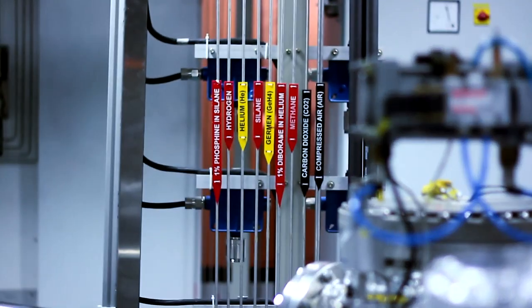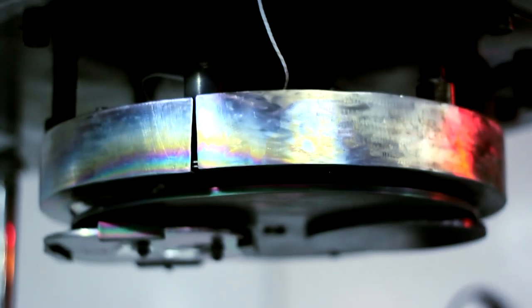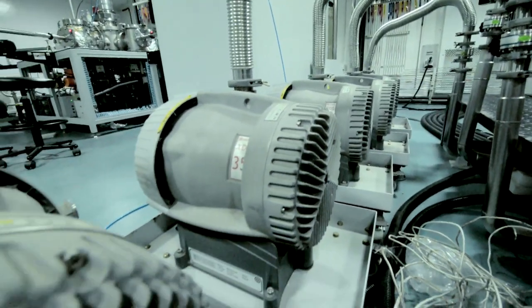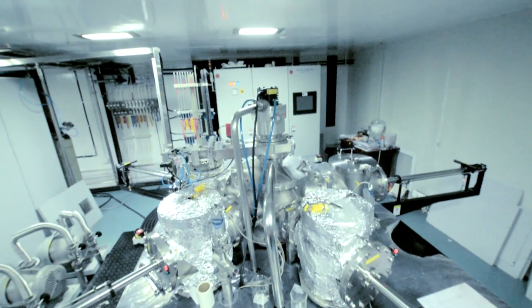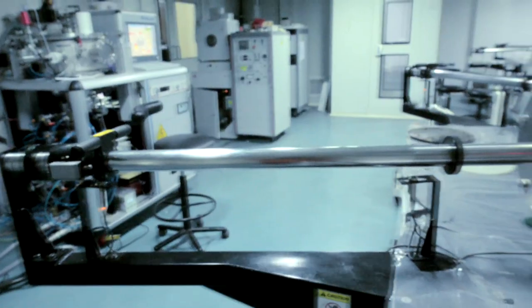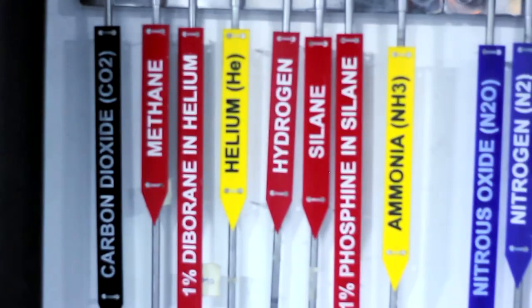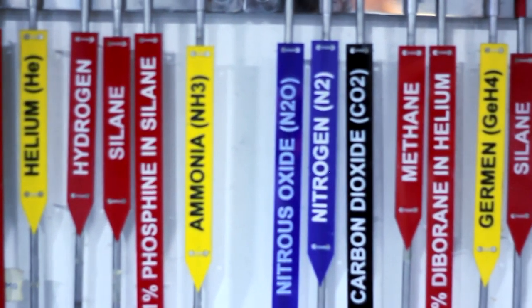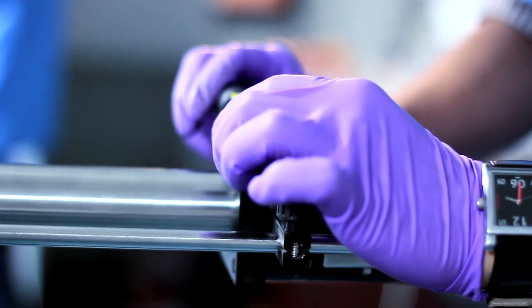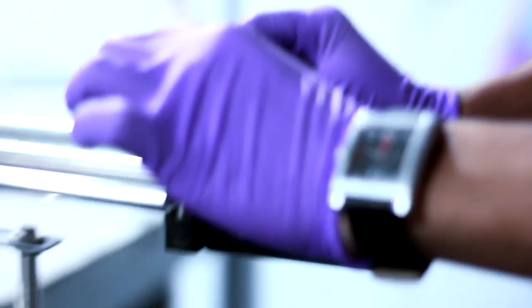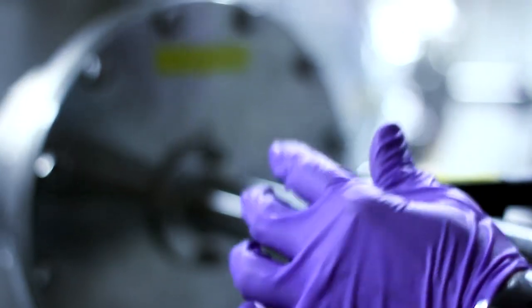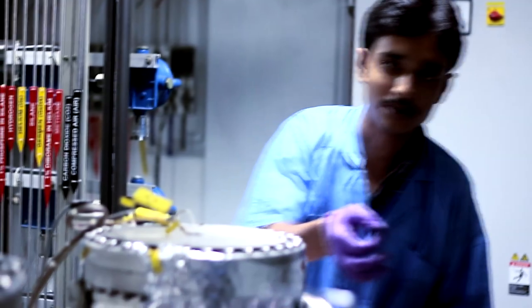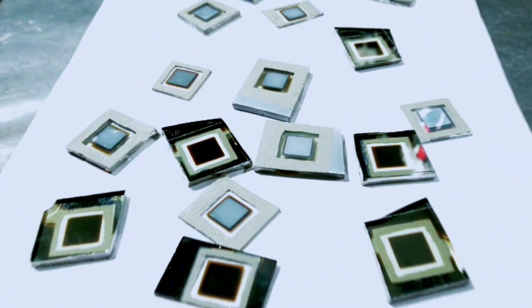State-of-the-art facilities for fabricating thin film amorphous silicon solar cells having an initial efficiency of 9.5% have also been achieved, which mainly involves a 5-chamber plasma-enhanced chemical vapor deposition cluster tool with several gas lines of specialty gases to deposit the amorphous silicon layers. The transparent conducting oxide glass superstrate is loaded into the system, and the amorphous P, I and N layers are deposited sequentially in separate chambers to avoid contamination before being finally unloaded.